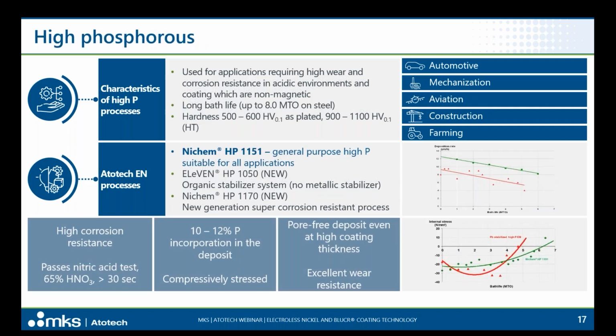In the high phosphorus range, we have our star Nichem HP1151, which can be used for general purpose of high P and is suitable for all applications. We have ELEVEN HP1050, which is our new organic stabilizer system. We have no other metals in the coating apart from nickel. And Nichem HP1170, which is our new process with a very good corrosion resistance.